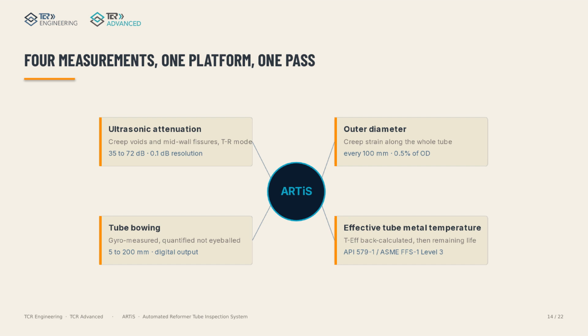The probe shoes seat against the tube and it climbs under its own drive, while the couplant feed keeps the ultrasonic contact wet. Every 100 millimeters, it logs an attenuation reading, a diameter and an angle. Nobody is on scaffolding. Nobody is holding a probe at 15 meters. And the record is continuous rather than a handful of spot checks.